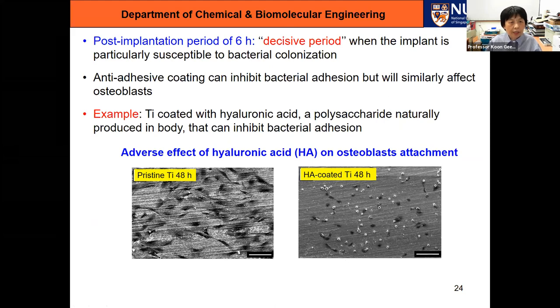And we've seen from our previous data that we can just put an anti-adhesive coating that can inhibit bacteria adhesion. But then it will also inhibit osteoblasts. I showed the data over here for one of our coatings. This is pristine titanium in the presence of osteoblasts. After 48 hours, osteoblasts adhere well, they start to spread, and that's because titanium is a good substrate for implants. But if we coat it with hyaluronic acid, which is a polysaccharide produced by our body that can inhibit bacteria adhesion, now we see minimal attachment and spreading of the osteoblasts. They remain rounded. And this, of course, will not lead to osteointegration.